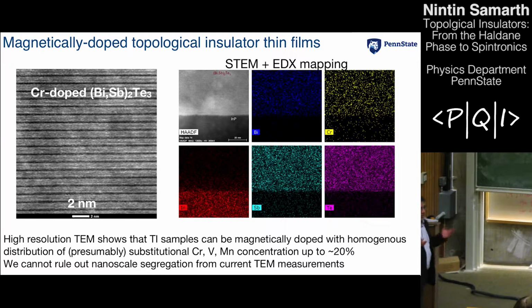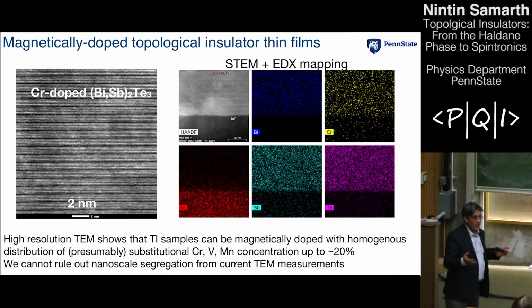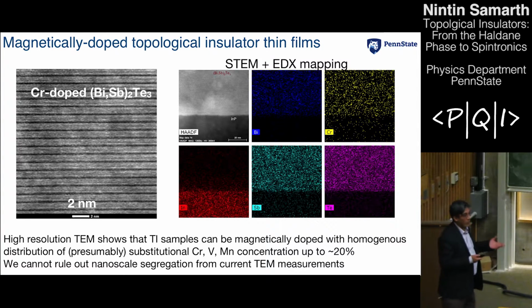So we can make these samples. We make the samples by taking one of these crystals that we are typically making in thin film form, and we introduce some magnetic dopants. So these are typically transition metal elements like chromium or vanadium or manganese or iron. So here is an example of some transmission electron microscopy. This is a cross-sectional view with electron microscopy where you see these quintuple layers being formed.